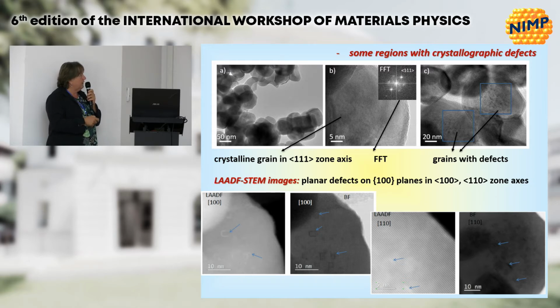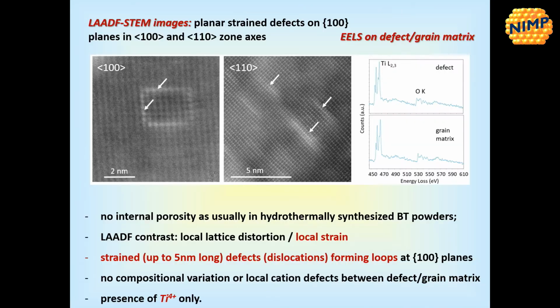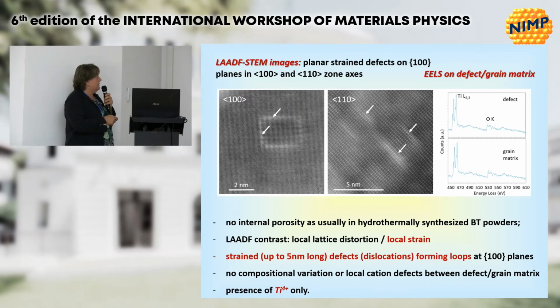But instead, what is very interesting and not reported yet, I don't know if you can see very well, there are regions with crystallographic defects, which are extended defects along 100 planes in 100 and 110 zone axis, which by low angle annular dark field mode, okay, here maybe you can see better, they demonstrated to be strained. So we have here internal strains in the starting powder. Again, no impurities around this one. The composition is just the same around this defect and outside where we have no defect.